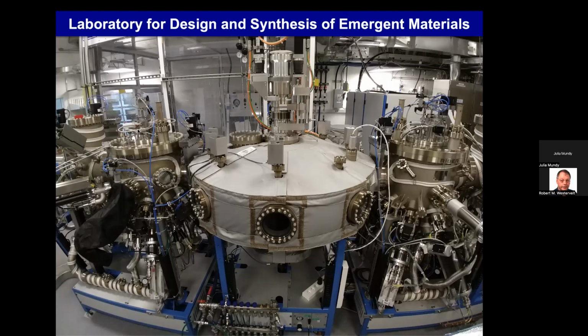So first of all, these MBE chambers are used commercially. This is how we make blue LEDs, and various other things. They mostly operate in a different regime that Professor Westervelt mentioned at the beginning, where it's self-limiting growth, not spending a week optimizing the growth. There are cheaper ways to manufacture materials: pulsed laser deposition, sputtering, chemical vapor deposition, ALD.